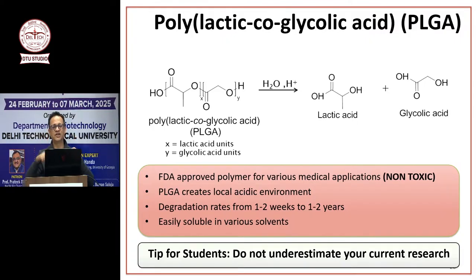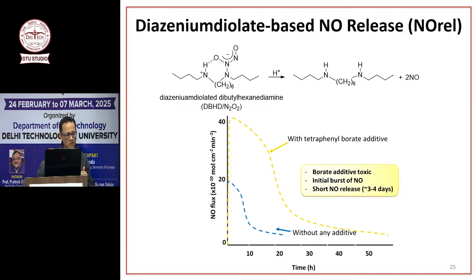I know for a catheter, I don't want a biodegradable material, right? But let's say 5% of my coating is PLGA, and 95% is polyurethane for strength. Our hypothesis was that when this reaction happens, when diazeniumdiolate, my nitric oxide donor, breaks, it forms diamine. At the same time, PLGA will also break and make acids. And don't worry, I know you're thinking, oh my goodness, the acid in the blood will change. We are talking about very minute amounts, only acting inside the coating. So at the same time you're making diamine and forming these acids, and the acids and diamines can neutralize each other, and the coating pH can remain neutral or slightly acidic. So this system can keep releasing nitric oxide.